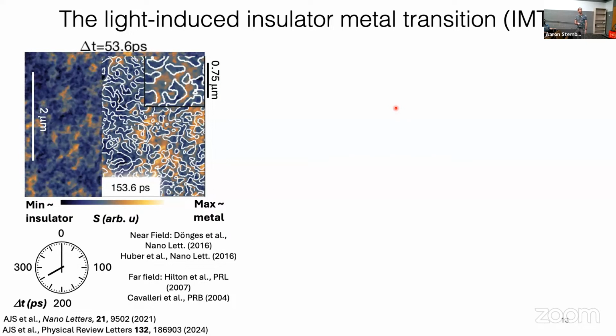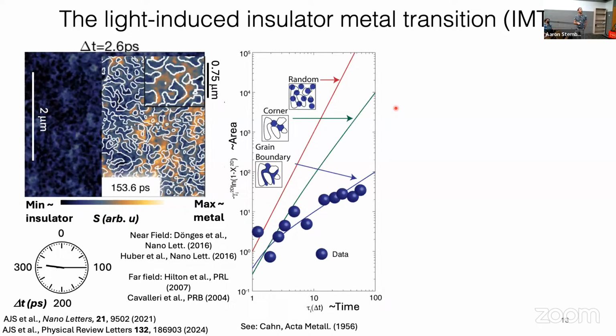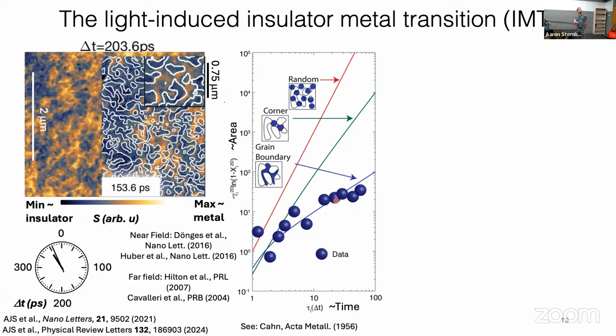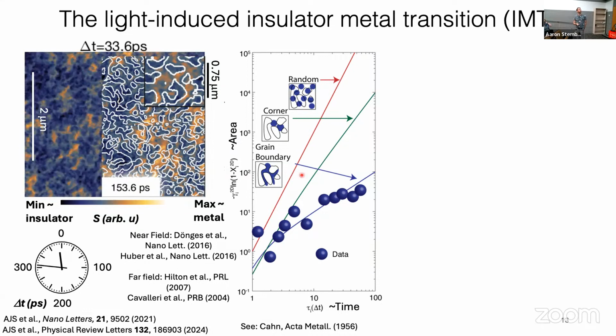And while this kind of observation could be impacted by field enhancement with the tip sort of buried in a trench and other things, we extracted the power law of how the area of metal depends on the pump probe time delay. And this agrees with grain boundary driven nucleation and not with other types of nucleation.